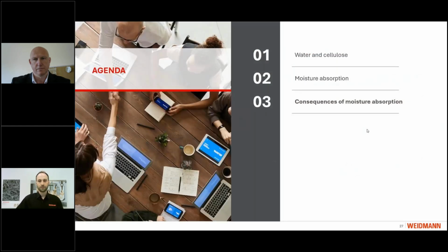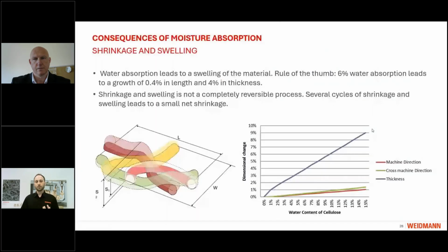So with this, we can look at the consequences of moisture absorption. First of all, it's important for you to know that due to the assessment that we have individual paper sheets that are stacked on top of each other to make the board, we can see that within the sheet, where we only have the fibers, we have quite a small degree of swelling, because the fibers which are covalently bonded will not swell so much. However, in between the individual paper sheets, we can have these hydrogen bridges and water coming in, which pushes the paper leaves out and generates thickness. So a general rule of thumb is kind of 10 times more swelling in thickness than in length or width.